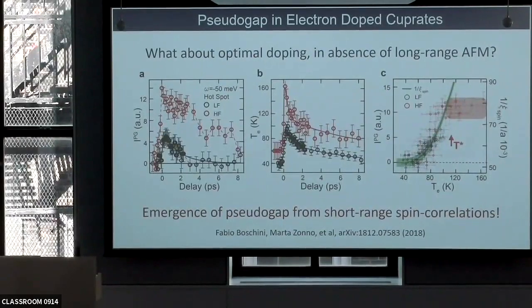And so again, if you do an analysis of the spectral function, you would see a gamma term become comparable to the size of the pseudo gap itself, and that's when the evolution of intensity stops. But the bottom line of this experiment is that you really see that the pseudo gap itself emerges as a consequence of the spin correlation, even though they're extremely short range. And so this really raises the question of how far in doping can you go? How short can the spin correlation length be, and yet still see an effect on the Fermi surface of the material?